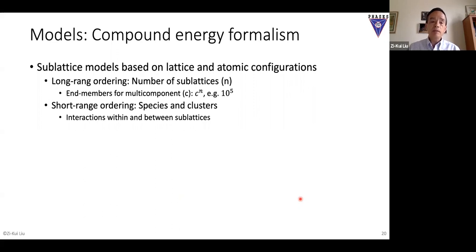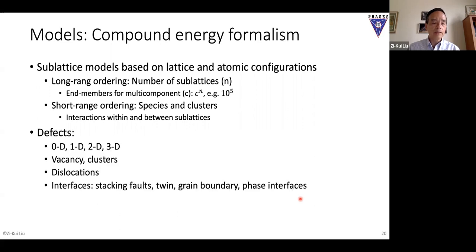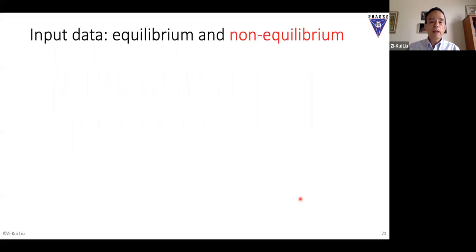So you need to take both the long-range ordering and the short-range ordering into account. And you have defects. The defects really determine our properties, right? So we have a way to get the defects into the model. You have the vacancy, anti-site, and then you have dislocations. This kind of thing has to be taken into account so we can make more use of computational thermodynamics. So input data, let's talk about input data, equilibrium and non-equilibrium.